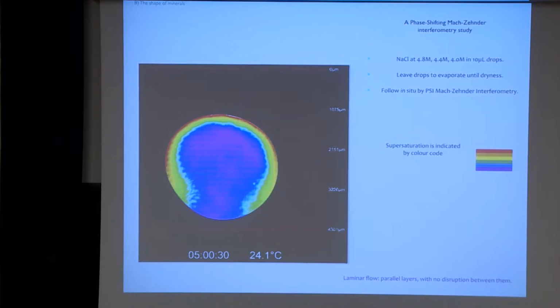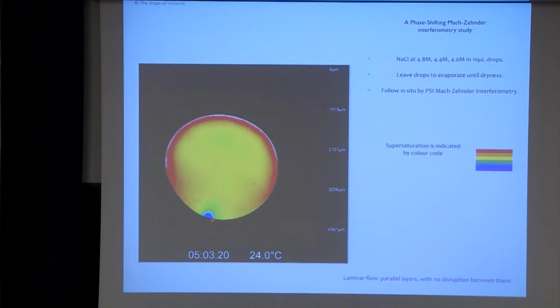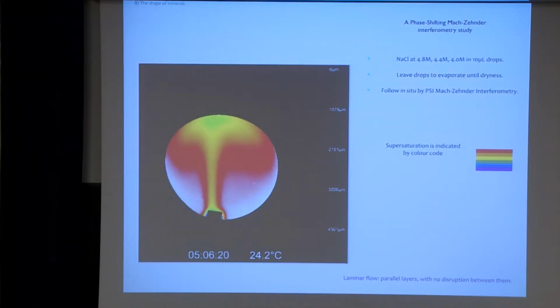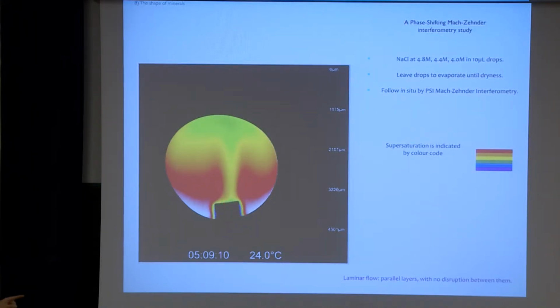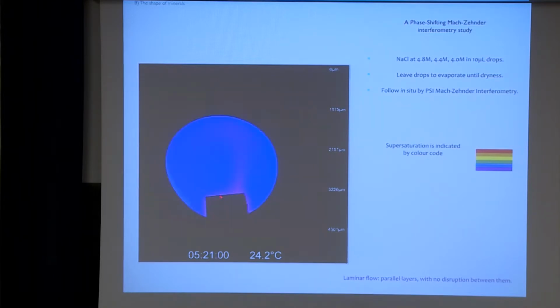So what happens is that, this is the video interferometry. You will see the crystal form, okay, fall down because of the gravity, and then you can see the growing phenomenon. Okay, what we have here is that because the growth of the crystal is fed with the solution on top, this part of the drop becomes less concentrated, and therefore you have a convection plume. And because of the convection plume, you have different growth rates for faces with the same symmetry, with the same anisotropy. Okay, but these two faces are growing faster than this face here.